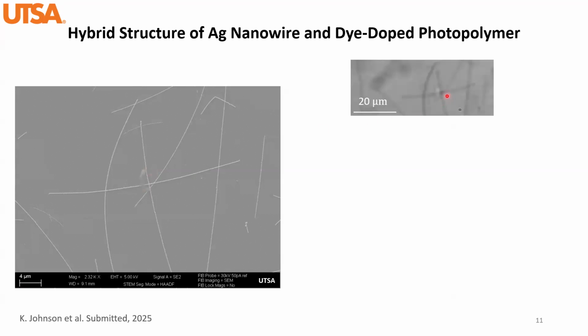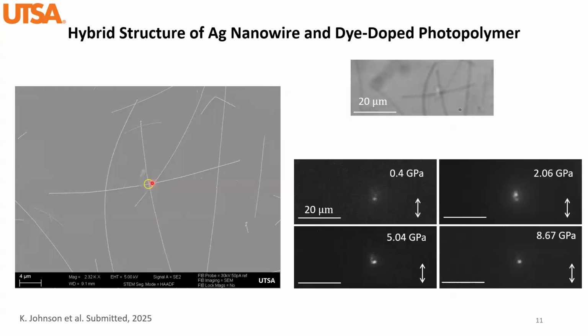This is how it looks under our microscope. The SEM image tells us more details about how the bridge looks. And this is our laser spot, which is pretty big compared to the size of the nanowire. The bottom of this tiny polymer bridge is probably affected by the laser spot, so just use that one as a reference. However, the top parts of this bridge are outside the laser spot. So when it lights up, it tells us the surface plasmon is there.